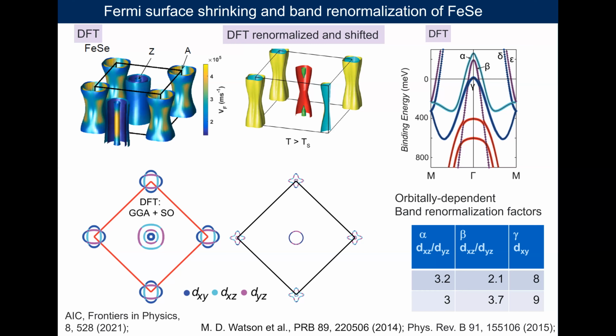And quick question. Not only did that gamma band not seem to cross the Fermi level, but it didn't seem to be there at all. I'll show you in a minute. These are very high temperature data. So when we go to low temperature, we start seeing that band from the hybridization. At high temperature, things are getting fuzzier, and when there are weak effects, you can't see them, unfortunately.